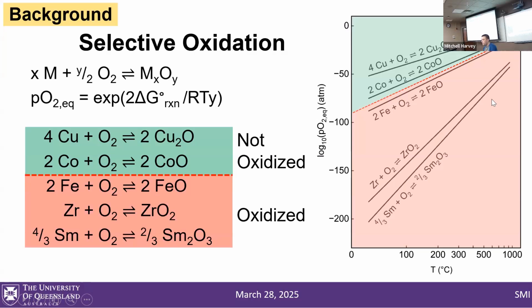Unfortunately, cobalt and iron are very similar. They're not quite as similar as cobalt and nickel, but they're harder to chemically separate. And if we're going to try to retain the cobalt as the metal, we want to oxidize the iron away—so we force the iron to the oxide phase. The zirconium and the samarium are going to oxidize very easily. So we're going to control our oxygen partial pressure such that we don't oxidize the cobalt or the copper, but oxidize the iron, zirconium, and samarium.